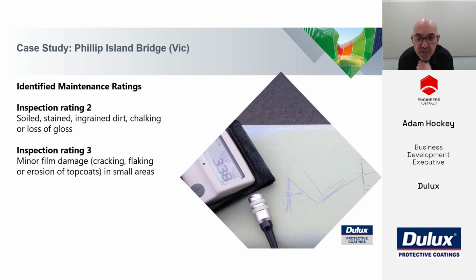So we're doing our inspection of the guardrail a bit closer now, and we've got our dry film thickness gauge, which measures the microns. So it measures the coating thickness. And by that gauge, we can see we've got 338 microns of coating still in place after 20 plus years. The original coating system would have only been specified at 325. So it hasn't grown. It would have been applied at a higher application than what was specified. But by measuring that coating thickness, we haven't really suffered any loss of the protection of the coating system. What we've suffered is the top coat has broken down. So the colour coat has either chalked or eroded away.